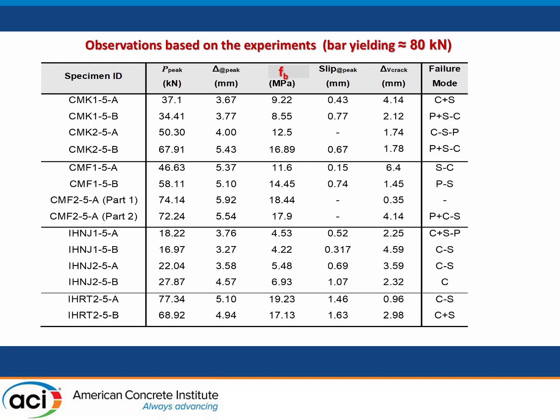Note that about 80 kilonewton would correspond to bar yielding. So you see that in some situations, just 5D were able to reach almost bar yielding. We didn't yield it, but it was very close. And the bond stresses that developed in this very, very small cover ranged between 9 and almost 20 megapascals.